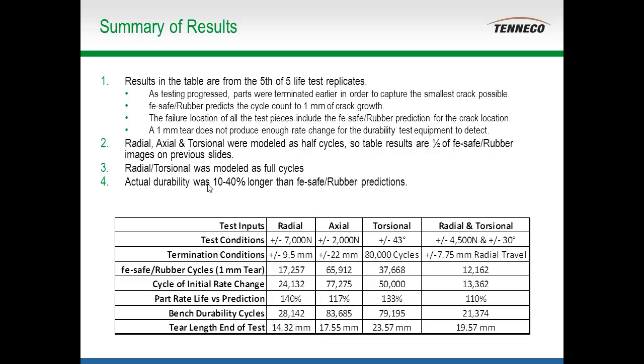But of the 4 cases we were able to do, between our predicted FE-safe rubber cycles and then from the actual displacement or force drop-off curves, our cycle count of earliest initiation or earliest indication of a rate change within the part. To what I just said on the integration from a very small crack to a 1 millimeter tear, many products at a 1 millimeter tear, you won't have enough of a force displacement response change that a test machine is going to be able to detect a crack that small. You know, the wall thickness on this part is 18 millimeters, so a small crack internally of 1 millimeter may not give you much of a force displacement change. So from a durability test equipment standpoint, we can't terminate it at a 1 millimeter tear.